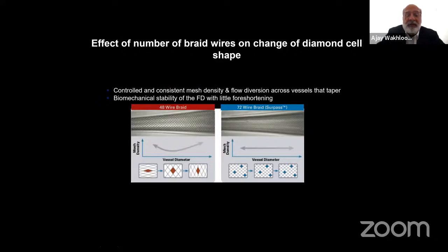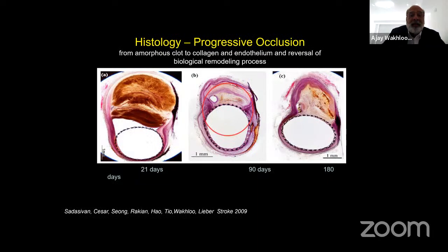Now, other advantages of having tighter mesh is that the geometry of the cell size naturally doesn't change much. So if you cover a long segment of an artery with mismatch in diameters of the vessel, you will recognize that the tighter the mesh, the less there is a variation in the cell size and the shape of the cell. That's what we call a consistent mesh across the segment that is being treated. Why is that important? It's important for the exchange of the blood flow between the parent artery and aneurysm. It avoids these gaps of blood flow going into the aneurysm that potentially may lead to rupture. This is how it looks.